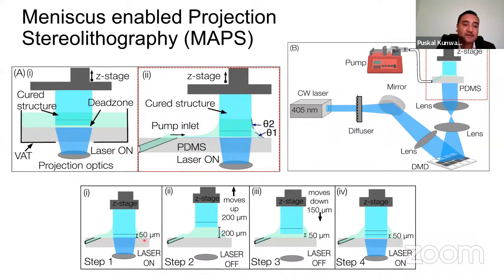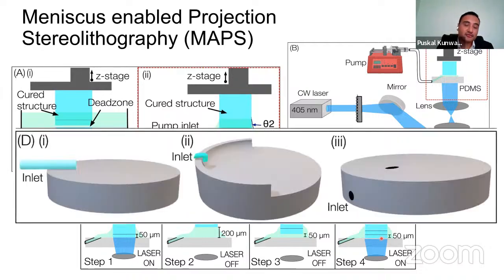Let's say you want to print a 50 micrometer layer. What happens is the stage moves up, drawing enough material for printing 50 microns, then it goes down 150 microns, leaving a gap of 50 microns. Then the laser turns on and cross-links the 50 micron gap. This iteration completes the whole structure. Now, just to avoid confusion, in this work we have used different configurations for the inlet tubes. It can come from the side, from the top, or from the bottom. You will see different configurations in different experiments as this presentation progresses.